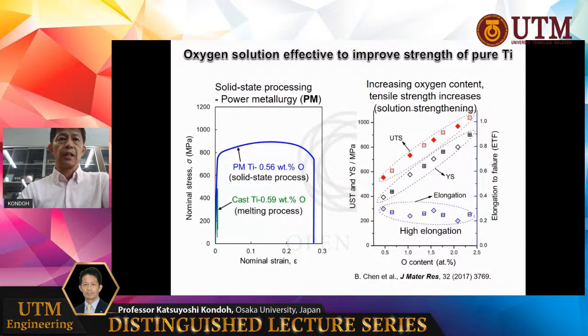This is mainly due to the oxygen atoms uniformly distributed in the alpha titanium grains. For example, on the right side, with the increase in oxygen content, UTS and yield stress gradually increase. And of course, elongation shows constant values. That means sufficient ductility is kept in titanium alloys with a high concentration of oxygen atoms. So as you probably understand, the powder metallurgy process has a very large possibility to improve titanium materials performance by using ubiquitous elements.